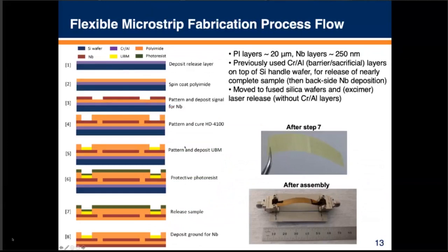Here's a representative fabrication process. In our older processes, we were using this chrome aluminum release layer and then doing a multi-layer thin film process on top of that. Our polyimide layers are somewhere in the range of 10 to 20 microns, and the niobium layers are around 250 nanometers. And so you can see the stack up here. We can subsequently deposit polyimide, and niobium, and build the structure up.